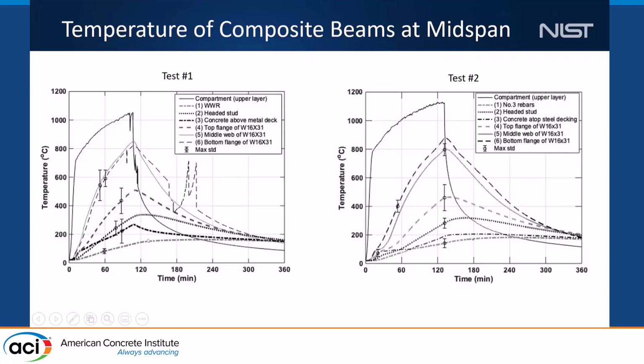However, the temperatures of the reinforcement embedded within the concrete topping above this protected steel beam evolved much slower and stayed smaller. However, as you can see here, the thermal response between the two tests is pretty comparable.